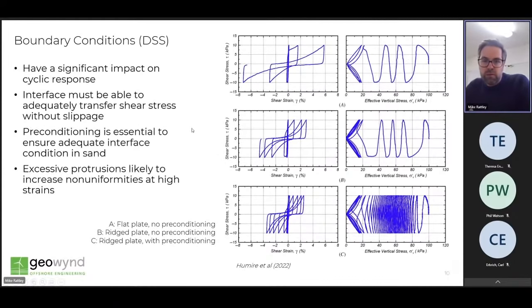As noted earlier, it's also important to understand the boundary conditions imposed in the DSS test because these have a significant impact on cyclic response. And the illustration on this slide is taken from some recently published research, which highlights the impact of the loading platen configuration. So those interfaces we discussed earlier. Three results shown are generated on similar specimens of clean sand. The upper plot shows the result for a flat interface plate, so we're up here, with no cyclic preconditioning.